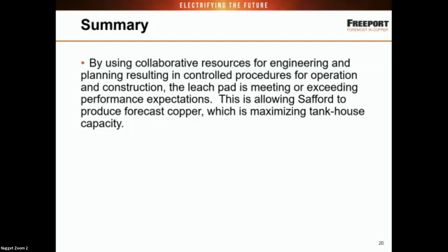Okay, acid consumption. So your acid consumption and downstream effects need to be considered. For an oxide copper deposit, our PLS was expected to have low initial acid because of the column testing that we had done. We really anticipated that, especially since we were neutralizing that ROM layer, we figured we might be really low on acid. As it so happened, it really did not use as much acid, and we had more free acid in our PLS than we expected, which resulted in lower pH, which in a copper extraction, that's a negative.